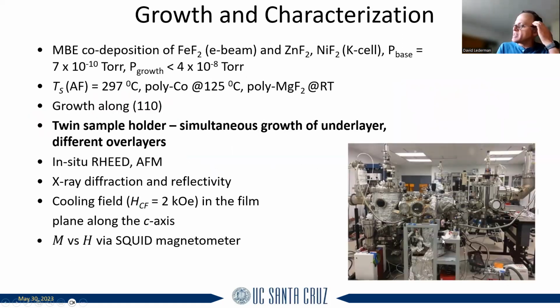These are some details of how we do these things. We have an MBE system. It's got multiple chambers. We use the different chambers for different things. This is the chamber that we use for our fluorides. The fluorides, they evaporate when you heat them up. We can do this using electron beam evaporation or thermal evaporation. And in this case, the fluorine bond to the transition metal is extremely strong, and therefore the thing evaporates as a molecule. Okay, and so in some sense it's easier to grow than an oxide, where the oxygen bond for a transition metal oxide is relatively weak, and so you lose a lot of oxygen, so you have to add oxygen. Here you don't really need to do that.